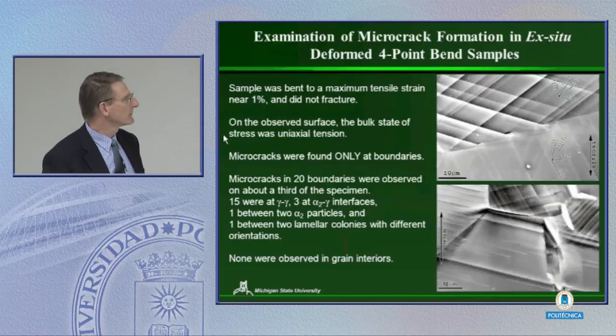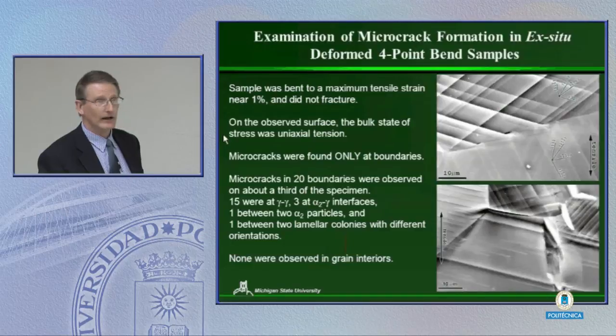But we found that the majority of 20 boundaries we saw cracked, the majority, 15 of those, were at gamma-gamma boundaries. 3 were at alpha-2 gamma boundaries. One of them was between 2 alpha-2 particles, and one was between a couple of lamellar colonies. And so we're going to focus on these right here. Where do these boundaries crack?